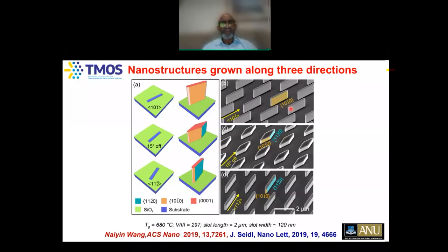If you open the slot along another crystallographic orientation, which is shown here, and you do the same thing, you can see that you can get membranes which are much thicker with respect to these ones. But also in this case, you got a different type of facet here, for example. So really this becomes thicker because some lateral growth is taking place, leading to this thicker membrane. And if you open the slot in between these two orientations, you can get these beautiful diamond-like structures with these alternating facets which I've shown you in these two examples.